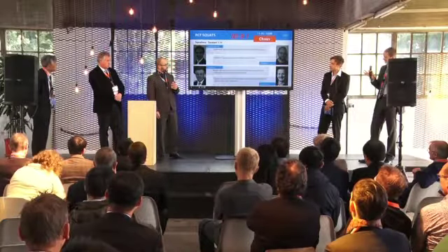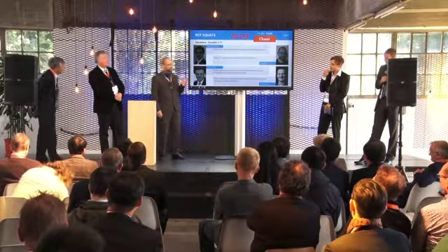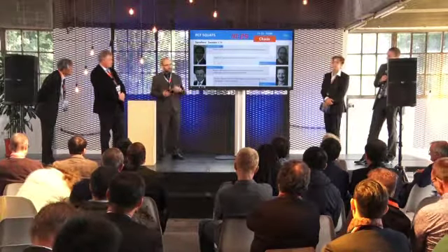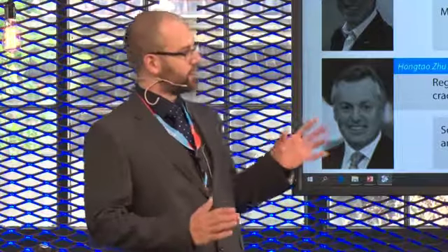Yeah, when I talk about thermal damage, I'm not really referring to the white etching layer too much. I've looked into the white etching layer and it is present in islands, but because white etching layer exists across all of the rail, I wasn't looking at that to be the cause. I was looking for something that was only existing within the defect. So yeah, by thermal damage, I'm referring to grain refinement rather than the white etching layer.